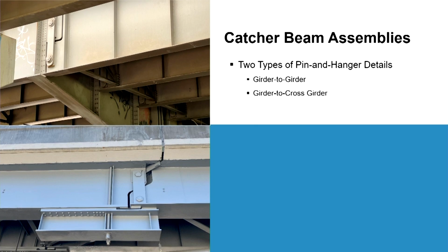There are those pinned connections that Ahmad mentioned on two of the structures, the 1104 and 1109 steel structures. The 1104 structure, which is shown similar to the image on the bottom of the screen, that one's from another project as an example, is a pin and hanger type connection that's mid-span between two longitudinal beams. And so we'll be implementing a fairly standard catcher beam there as an additional protective measure in case that non-redundant pin and hanger connection does fail. Hopefully this catcher beam never needs to be used, but if the pin and hanger does fail from fatigue loading at any time, then the catcher beam is there to prevent a catastrophic failure of that beam dropping away.